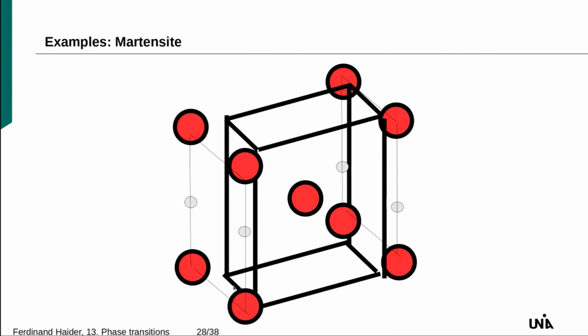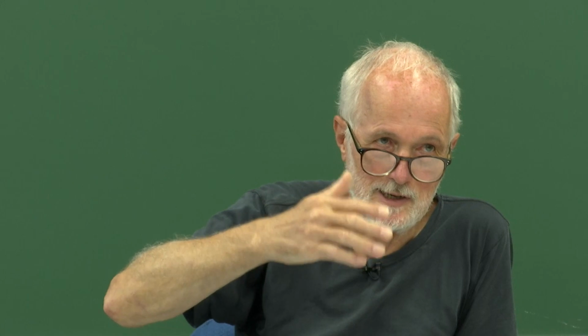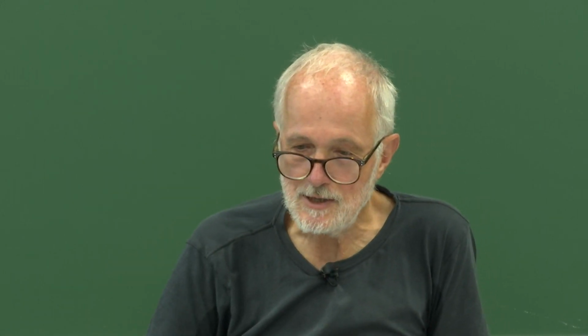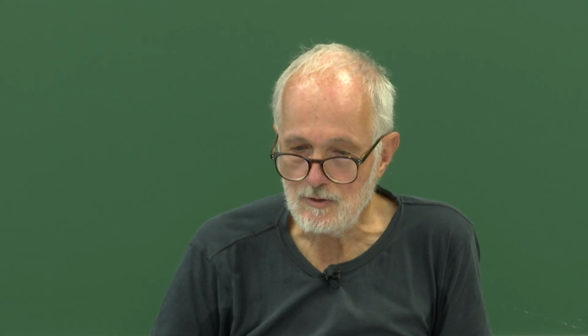And since this tetragonal phase can have different orientations, like this, or like this, or like this, you have different variants, and this huge number of variant boundaries, they prevent dislocations from motion. So that's basically the martensitic transformation.